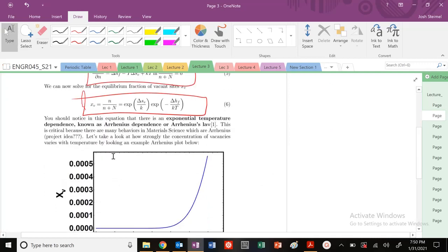And this expression is incredibly powerful because the concentration of vacancies, you can see here, has this exponential relationship with temperature. So as temperature increases, our concentration of vacancies increases exponentially. This general relationship, where you have an exponential of minus something, usually it's an energy, so some type of energy G,